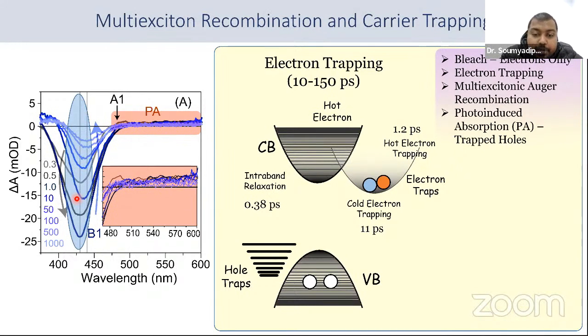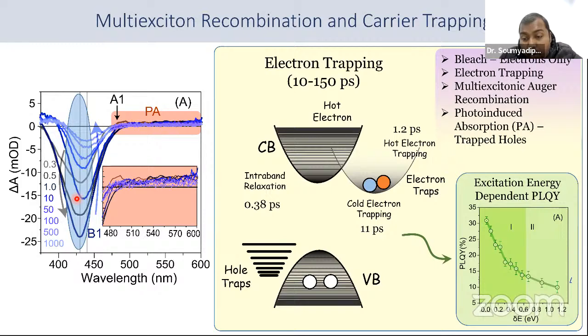we can see the time scales: intraband relaxation occurs at around 380 femtoseconds, hot electron trapping comes around 1.2 picoseconds, and cold electron trapping is rather slow, 11 picoseconds. Now, why do we say this is happening? Because when we are exciting the quantum dots far from their band edge excitation, we are getting a steep decrease of photoluminescence quantum yield. This is because of the electron trapping.